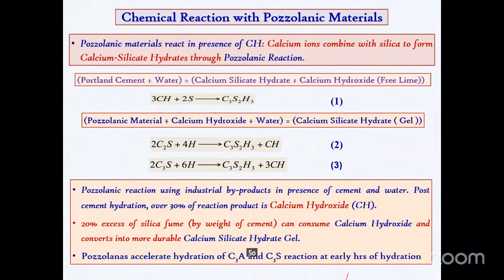So there, in equation number 2 or equation number 3, you find C3S2H3, that is a calcium silicate hydrate. That is the one actually going to change the internal structure and the performance of concrete, because the inert materials will not participate except in filling the volume. The one actually, calcium hydroxide plus SiO2, you will get a kind of C3S2H3. That is the one, whether it is a stronger one or just a weaker one, that will decide the final